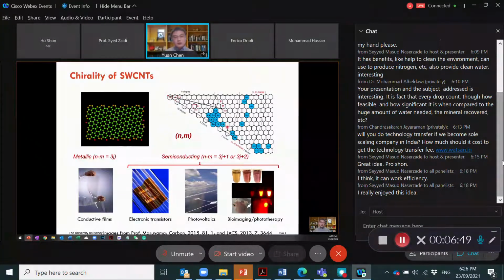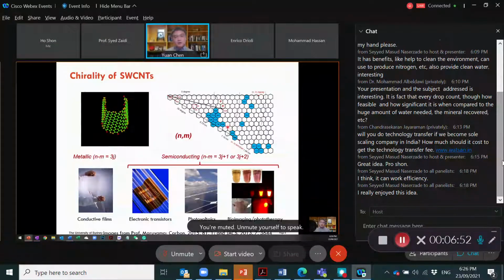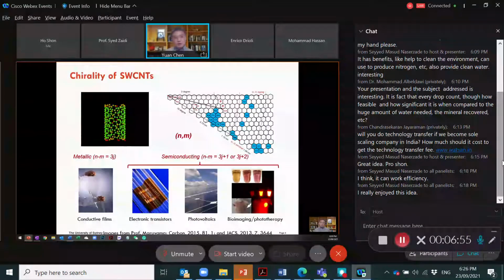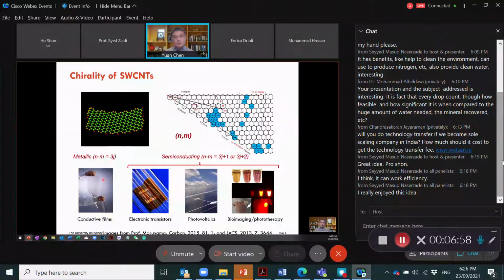So that rotation basically controls their electronic and photonic properties. So you get about a 1/3 chance you will produce some metal which is highly conductive, but then you have a 2/3 chance you will create a semiconductor with different band gap. So again, you can imagine if you want to apply it into application, if I want to have a conductive film, I actually need a high purity metal one. And then if I want to have a semiconductor used in electronics or in photovoltaics or for some biosensor application, I do need a semiconductor, and the best with a precise rotation of the graphene layer control.